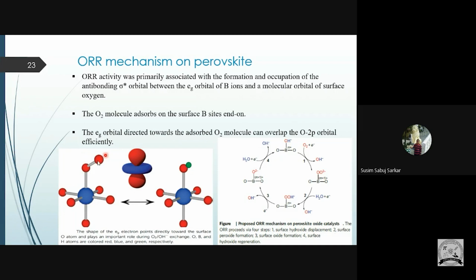Okay, so this is actually the reaction mechanism of this perovskite. Let us understand what is happening first. First, this is our transition metal oxide, that means the perovskite. So this is forming BOH minus. Now oxygen is coming and replacing the OH and forming BO2 minus. That means one hydrogen is getting removed and one oxygen is coming in. So the B is actually forming a bond with oxygen. Okay, then what happened? Then again, water is coming in with an electron and it's forming BOOH, and OH minus is getting out. Then this OH minus comes out easily with an electron, and it again forms BO2 minus, and again H2O is coming and we get back the previous form, that BOH minus.